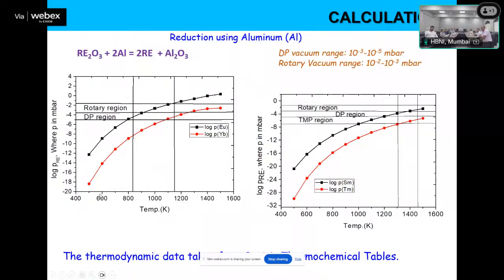So at this temperature, yes, rotary can reduce. And if you go on reducing ytterbium at 1200 degrees Celsius, there is a requirement of diffusion pump, DP vacuum; no, rotary will not work. And of course, for increasing the kinetics, you have to raise the temperature a little bit higher. On the right side, looking at the reaction with aluminum, it requires a very large temperature even to get into the DP region for samarium. So aluminum requires very high temperature for the reduction of samarium oxide. And for thulium, this is less.